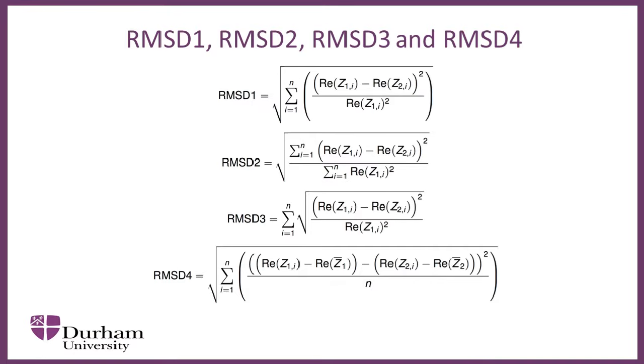It can be seen that the metrics obtained by transducers 1 and 4 under this condition are similar to those obtained under the previous two conditions, while an increase in the metric can be observed for transducers 2, 3, and 5. Under condition 4, one more 5 mm hole was located at x equals 20 mm, theta equals 90, in addition to the damage under condition 3. Again, there is no significant increase in the metric observed for transducers 1 and 4, while a marked increase can be seen for transducers 2, 3, and 5.